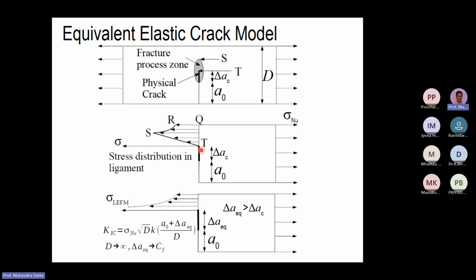And if you see the physical crack which has developed, there is zero load carrying capacity in this. So initially the crack was here, and as it progresses, this is a physical crack which has formed during the loading process. So in this region the material cannot take any more load, but in this region, it can still take some load, and that is represented by this stress strain diagram.